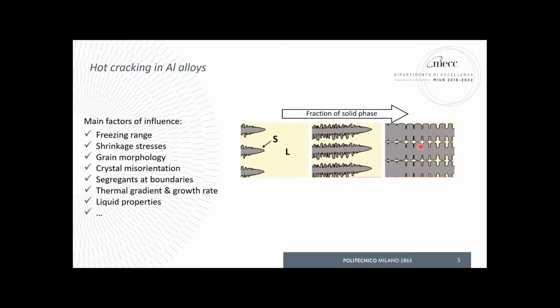In the very last stage of solidification, we all know that we may have a large fraction of solids. Still, we can have some films or some pockets of liquid, the yellow zones. And when shrinkage stresses are set up, because we may have some bridges that are connecting the dendrites laterally, we may induce solidification cracks, or hot tears. There are several names for the same phenomenon, basically. What can we do against that? Well, there are many strategies. Let us talk about a couple of them.